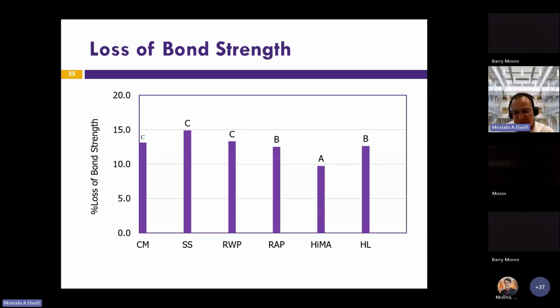In terms of bond strength after conditioning, the best performance was the HiMA, which had less than 10% loss after conditioning, followed by the RAP and the hydrated lime. And then the third group was the control mix, the steel slag, and the recycled waste plastic.